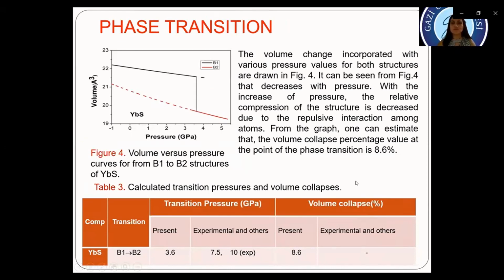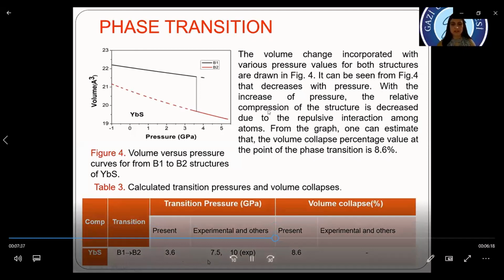It can be seen from figure 4 that the volume decreases with pressure. With the increase of pressure, the relative compression of the structure decreases due to the repulsive interaction among atoms. From the graph, one can estimate that the volume collapse percentage at the point of the phase transition is 8.6%. Calculated transition pressure and volume collapse.